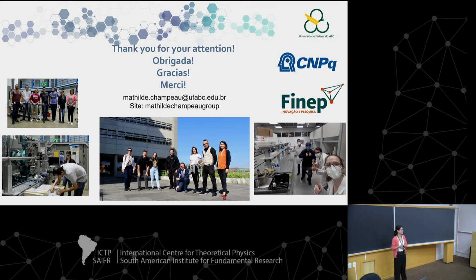Thanks, Mathilde. Very nice presentation. I have one more specific question regarding your first system that you showed with the pluronic and polyacrylic acid. My understanding is that it does not crystallize because of electrical repulsion. Is that the case? I'm asking because you have reduced the pH to protonate the acrylic acid part. Yes, it is protonated. What pH are you at? It's below 4. Okay, but you still have some percentage of charge. So maybe if you decrease a bit further, wouldn't you be able to form the gel? Because in this case, you can get a system that is responsive to pH in an interesting range. Yes, yes. We didn't test it. Okay. Yeah, it's right.